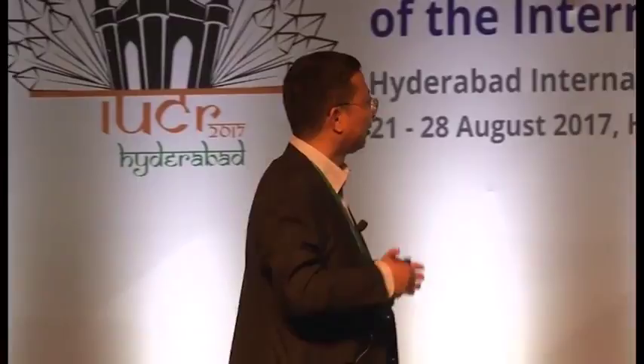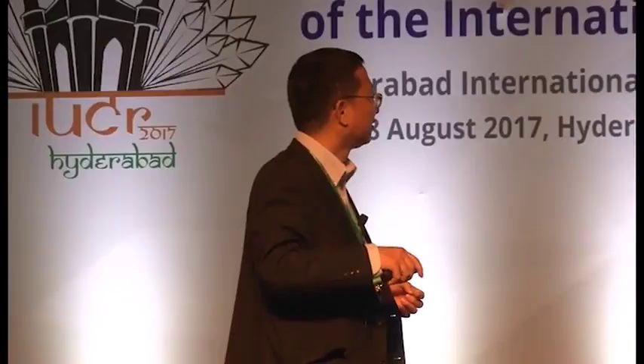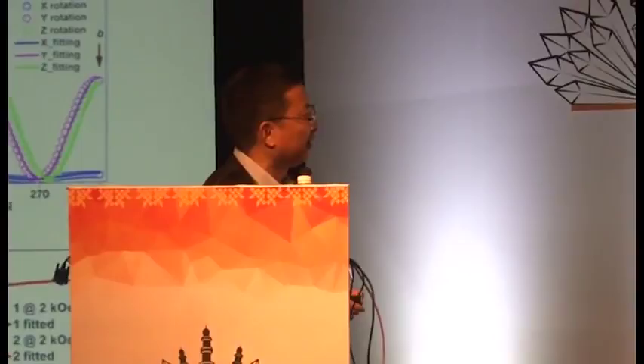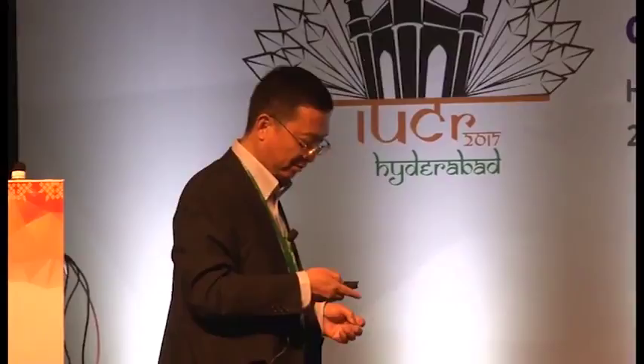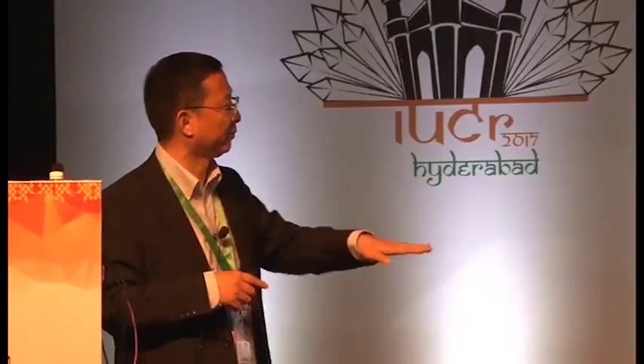For the series of compounds, for the COT, Tp compounds, not only the erbium compounds can show single molecule magnet behavior, but also the terbium. It's not a Kramers ion. It's the first time to observe single molecule magnet behavior in terbium compounds. They have a similar structure and the easy axis along similar directions, perpendicular to the COT planes.